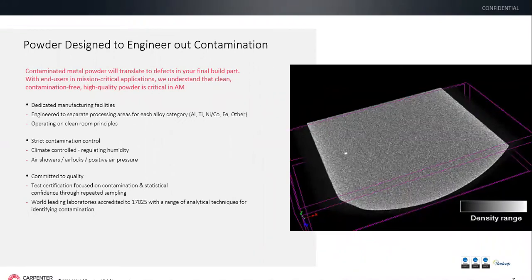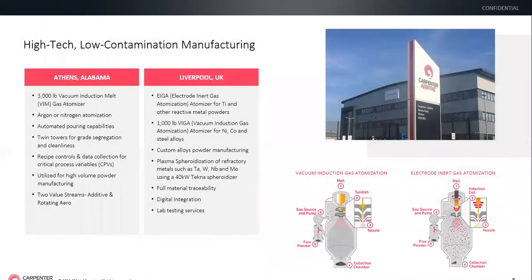And it reflects our commitment to quality, where we certify the powder on a robust repeated sampling approach, which leads to high statistical confidence. And our laboratories are accredited to 17025, which is a very stringent quality control certification, with a range of analytical techniques that we've developed in-house to identify contaminations. So as I said, high-tech, low-contamination manufacturing, and when you talk about titanium and other specialty alloys, we do that across two different sites, one in Athens, Alabama, and the other one in Liverpool, UK.